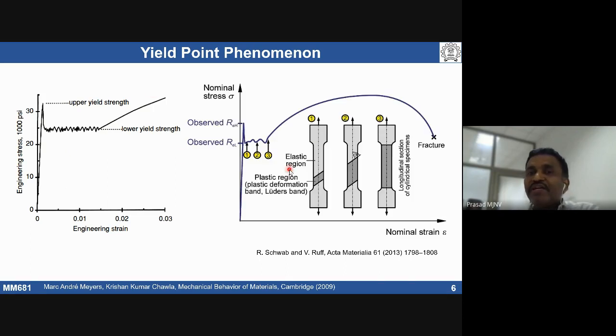If I take a stress-strain curve, just these three regions 1, 2, 3, and a tensile specimen, we already know there is a drop in yield stress, which means dislocations have been freed. So when the stress drops to this level, the tensile specimen is going to see formation of a band structure. This band is called a Lüders band. It will form at around 45 degrees, between 45 and 70 degrees. Where is it going to form? Wherever a stress concentration region is present in a specimen. In a tensile specimen, the first stress concentration region is always the fillet region. So that's why we see the band formation there.